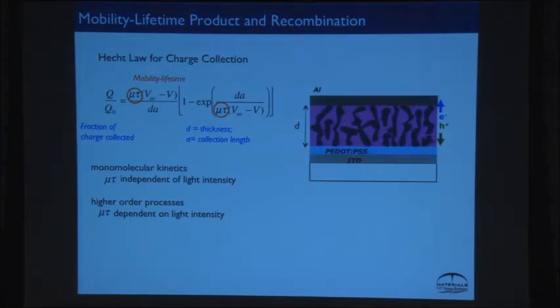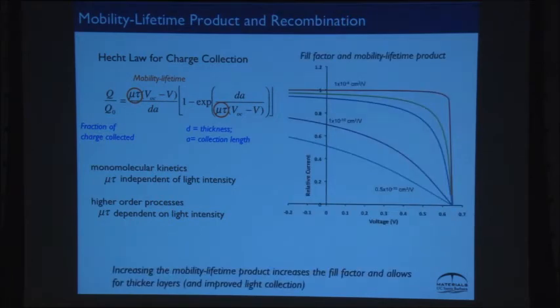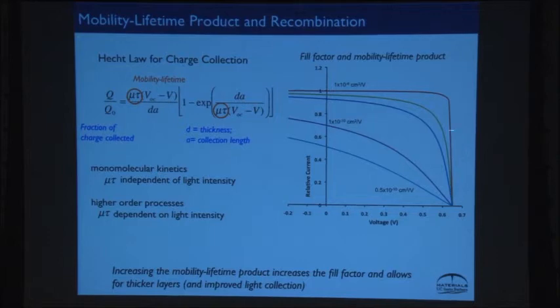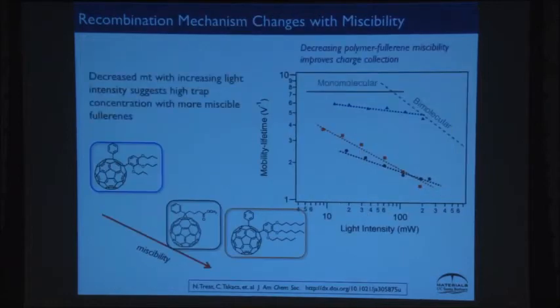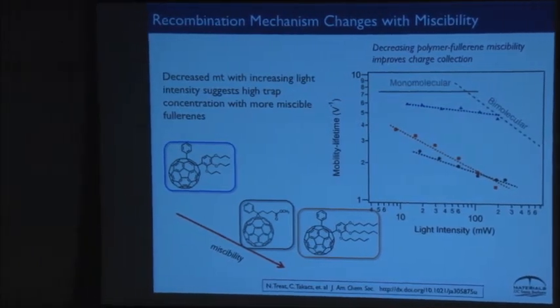If we take a look at this, you'd expect that if mu tau was independent of light intensity, you're going to be trap dominated. If it's dependent on light intensity, then you have bimolecular recombination. And if I look at this, as I increase mu tau, you get higher and higher fill factors. This is a standard analysis used for a lot of photodetectors. When we did this, we actually looked at the mobility lifetime product as a function of light for these cells.